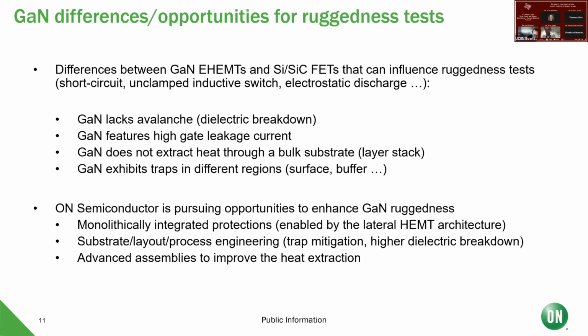But the HEMT structure intrinsically has very high gate leakage currents. You can also not extract the heat from the bulk substrate, but there's a lot of electrodes on the top to screen off voltages because the device is in principle in parallel planar.